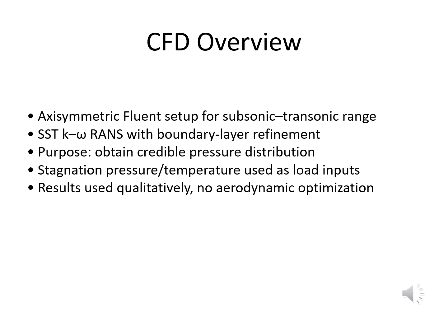The CFD portion of the project is not meant to optimize the aerodynamic shape of the nose cone. Instead, its primary purpose is to provide accurate pressure distribution along the external surface that can be transferred into the structural analysis. We use ANSYS Fluent to simulate axisymmetric external flow at Mach numbers from 0.3 to 1.2, covering subsonic to mild transonic regime. A structured mesh with an inflation layer ensures Y plus values close to 1, allowing the SST k-omega turbulence model to accurately resolve the boundary layer.